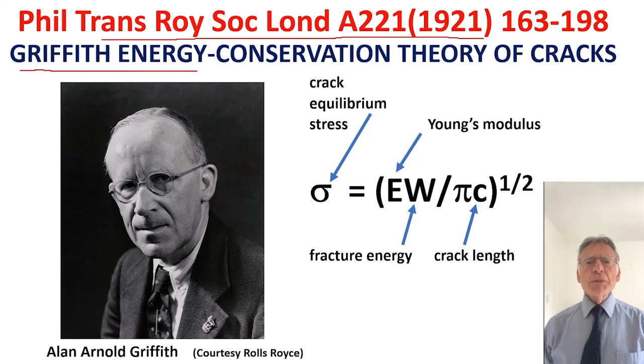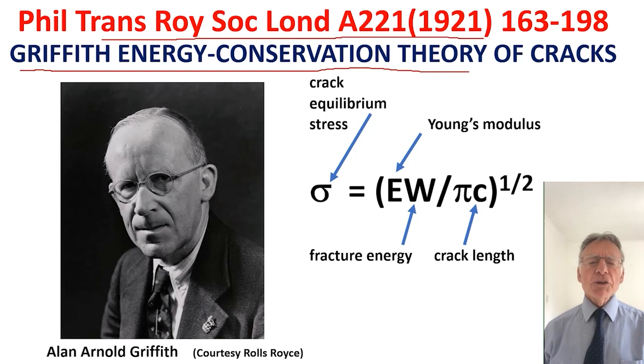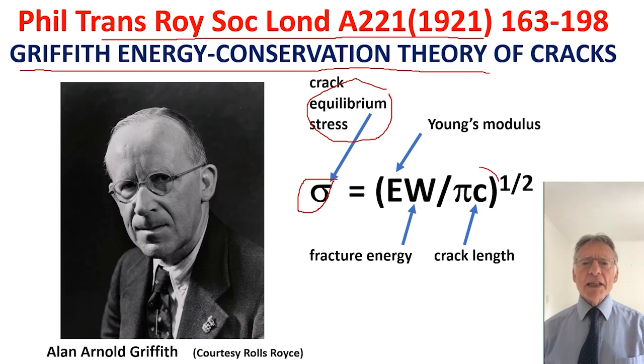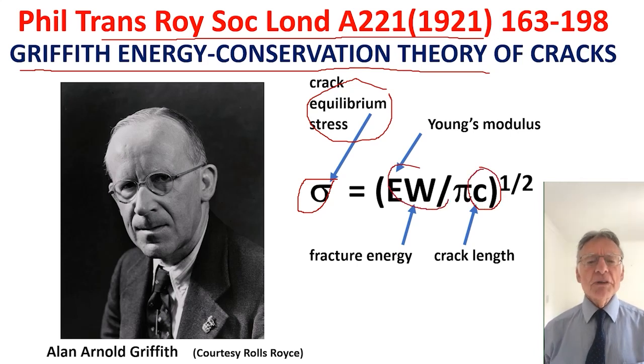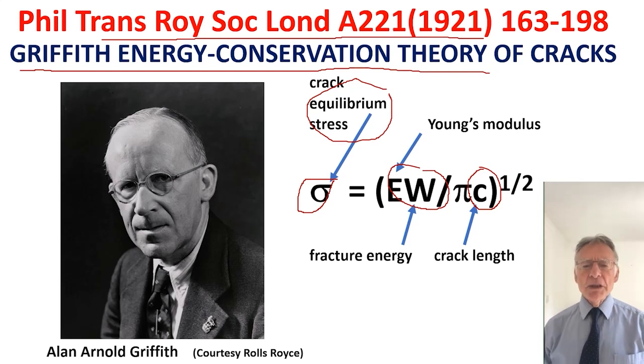In it, Griffith produced his famous equation from the conservation of energy principle, which seemed crazy at that time. He showed that the stress at crack equilibrium, sigma, went down predictably as the crack length c went up. And this required the new idea of toughness, W, the fracture surface energy, which is the energy needed to separate atoms against the atomic attractions as the crack proceeds.